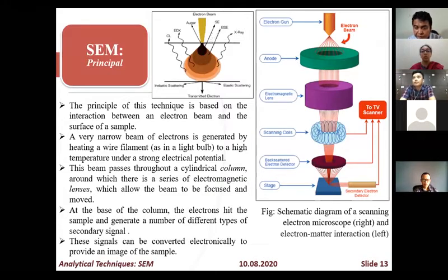Now, if you want to know the microstructure of our sample, then we must use another technique, the scanning electron microscope, or SEM technique. The principle of the SEM technique is also very easy, like XRF and XRD. It is based mainly on the interaction between an electron beam and the sample. If we see this chart, from the electron gun a very narrow electron beam is produced, and this beam goes through a cylinder surrounded by electromagnetic lenses, and then it hits the sample at the bottom and produces backscattered electrons, and these make a two-dimensional image.